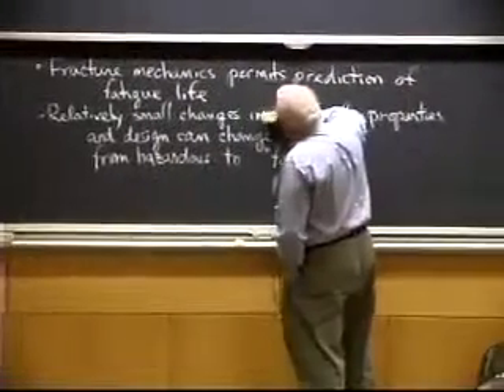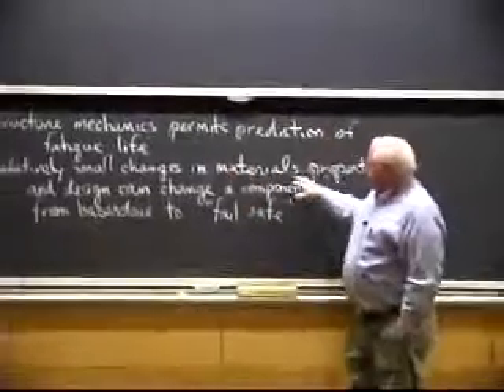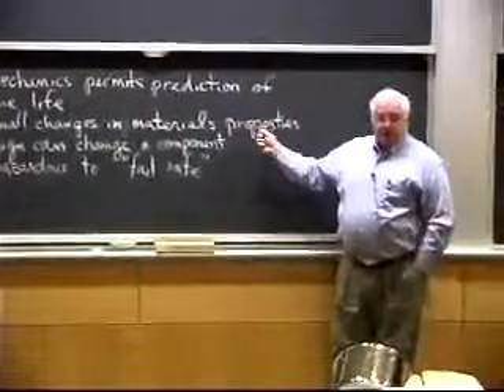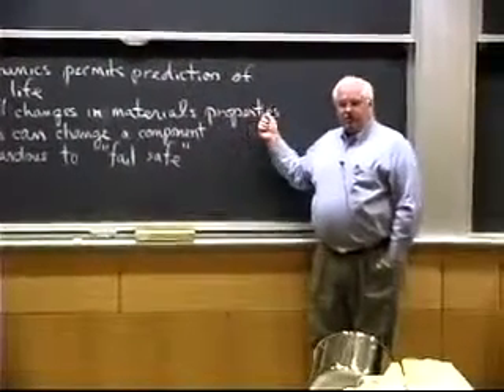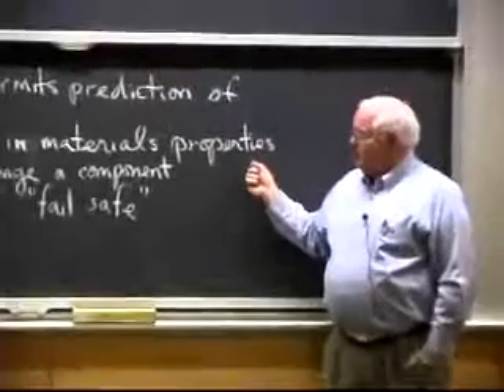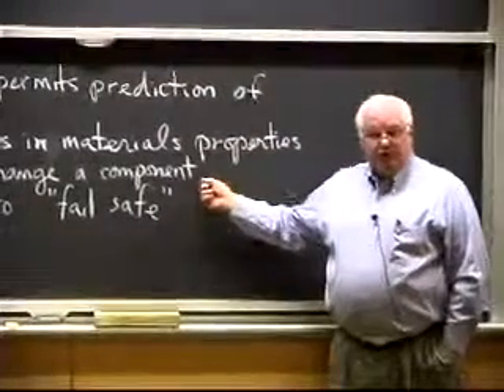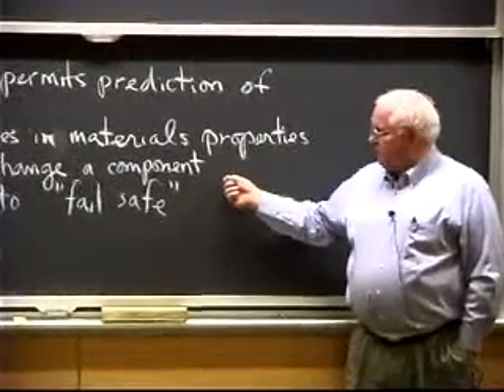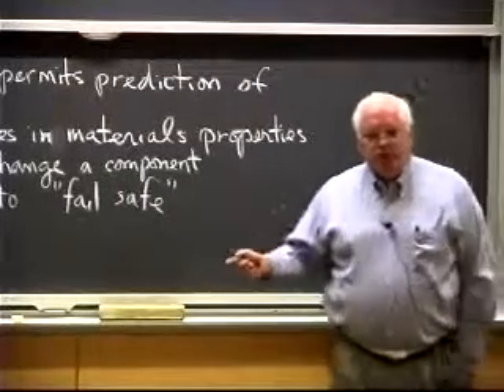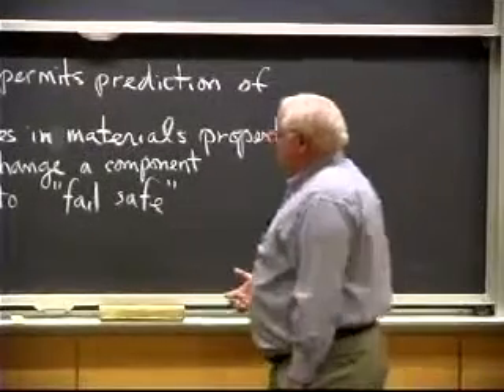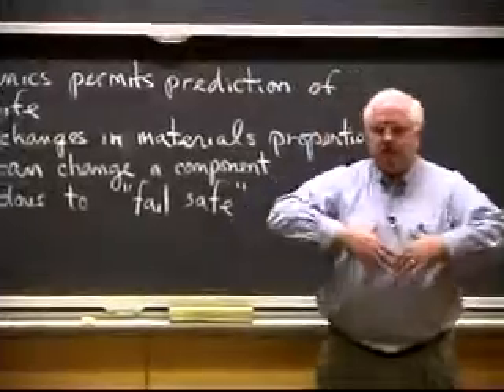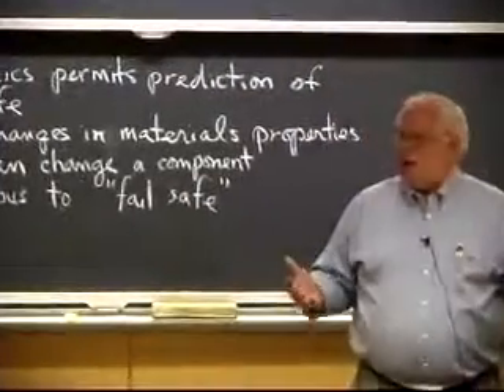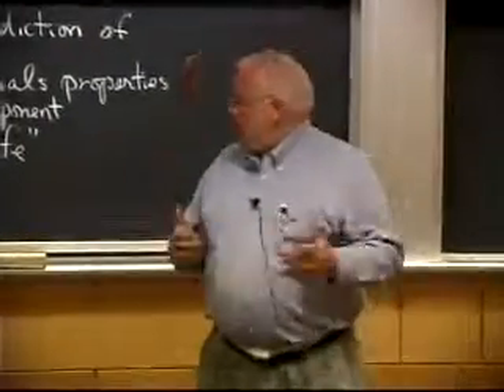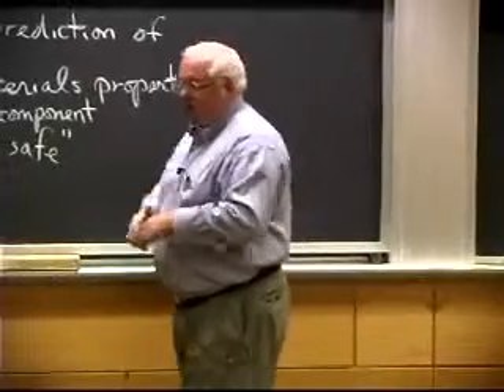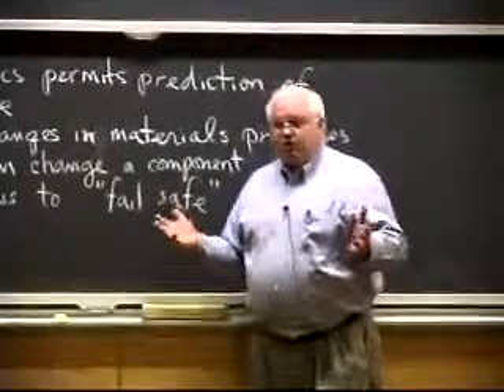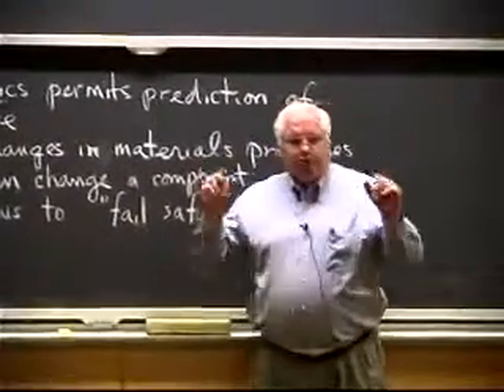But also I gave you the example of the hydraulic cylinder from the America's Cup yacht, where relatively small changes in the material's properties, changing the heat treatment so that the yield strength went from 73 KSI to 63, and the fracture toughness went from 26 to 30 KSI square root of inch, and the wall thickness went from 3 to 4 millimeters. Those three changes changed the component from something that was hazardous, that could just blast and blow apart in a catastrophic manner and spray high pressure oil all over everything and destroy the cylinder so it couldn't operate at all, to one that would leak before break.